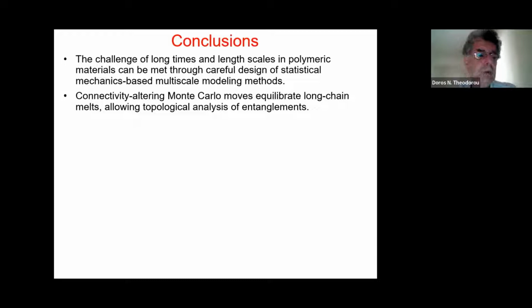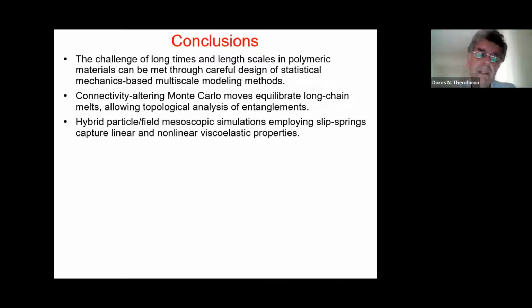If one wishes to look at the rheology, to look at the dynamics of polymers, one must necessarily go to mesoscopic or coarse-grained methods, and one should say quite aggressively coarse-grained methods. I described such a method, which is a hybrid particle field Brownian dynamics kinetic Monte Carlo, in which the parameters and the effective force field are derived bottom-up from atomistic simulations of low molecular weight analogs, and this can capture linear and non-linear viscoelastic properties.